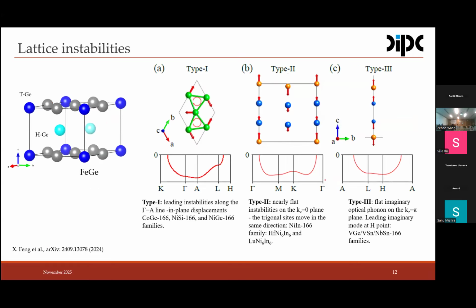And these charge density waves in the Kagome materials can actually be divided into three different types, depending on the eigendisplacement of the atoms that drive the imaginary modes. So we characterize these charge-ordered Kagome metals in three types. Type 1: the leading instability is along the Gamma-A direction and involves in-plane displacements of the transition metal atom. Type 2 presents a nearly flat imaginary mode along the Gamma-M-K direction and implies that the eigenvector of this atomic displacement is an out-of-plane, in-phase vibration of the transition metal plus the trigonal atom. And the type 3 charge density waves are actually driven by the condensation of an out-of-phase, out-of-plane vibration of the trigonal tin or trigonal germanium atoms in the unit cell.